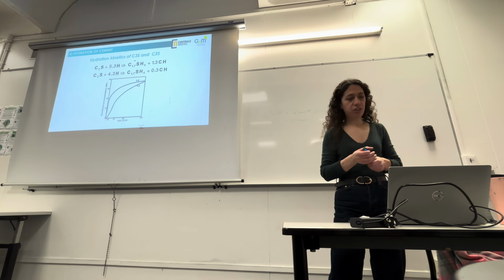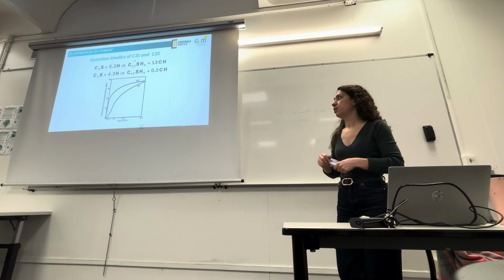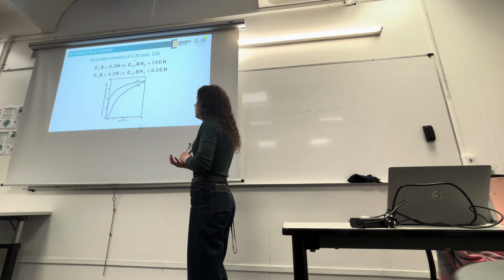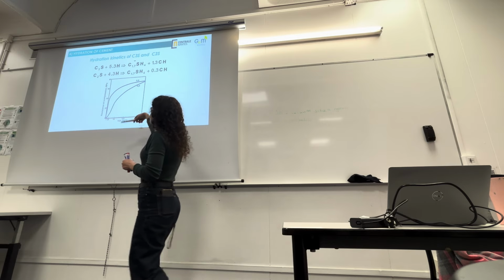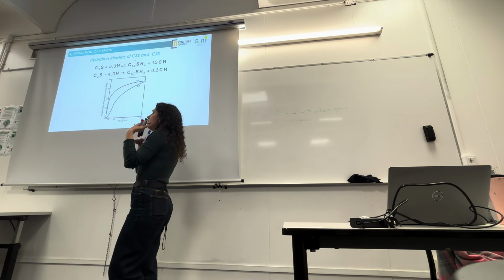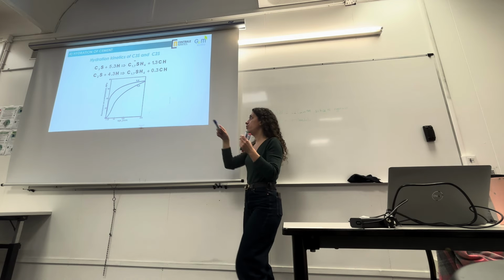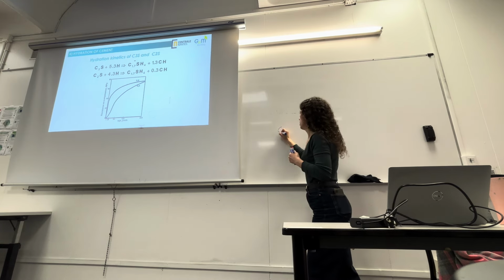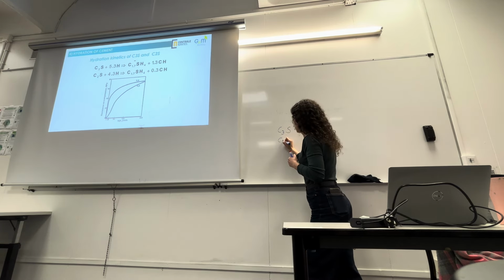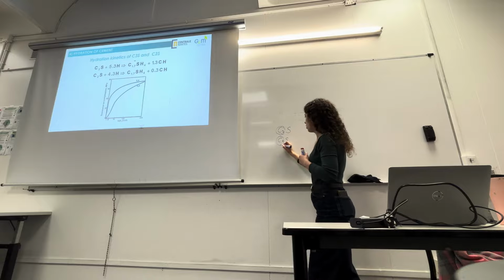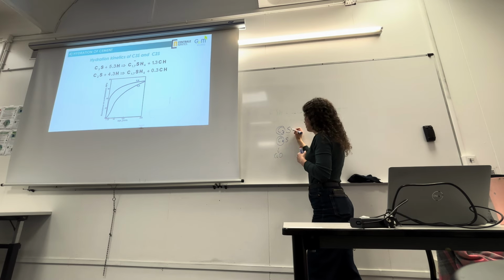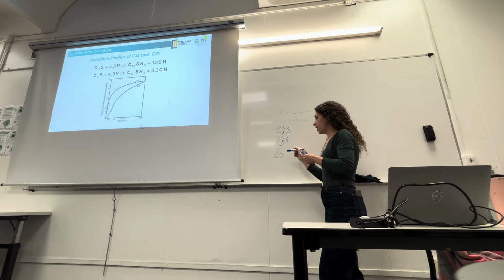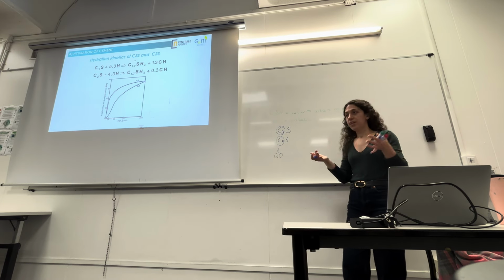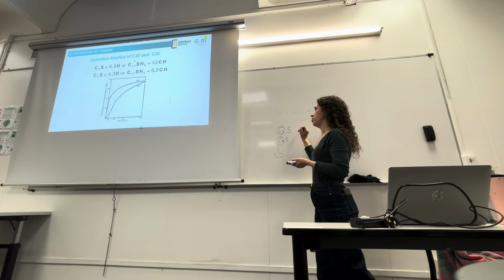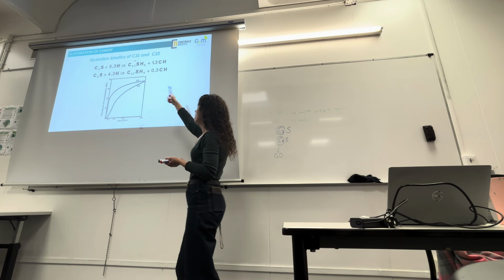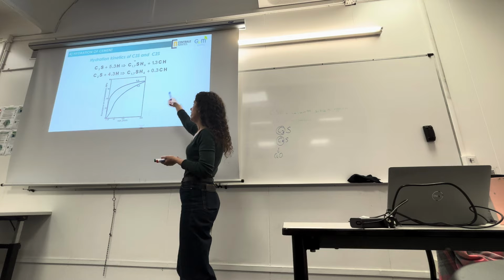Okay, so the hydration kinetics of C3S and C2S. C3S hydrates faster than C2S because C3S contains more calcium oxide than C2S. And calcium oxide is a reactive bond. So it will consume more water and form more hydrates, more CSH and more Portlandite.